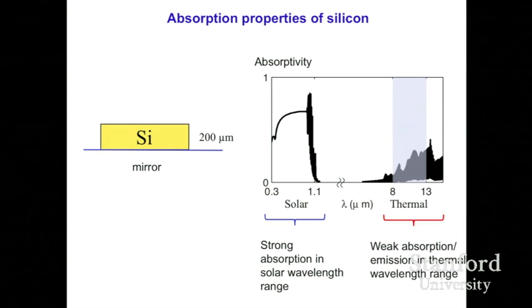So for that purpose, we examine the absorption properties of silicon over both the solar wavelength range as well as the thermal wavelength range in the 8 to 13 micron. In the solar side, of course, it's strongly absorbed. And it's also a weak absorber in the thermal radiation side, and therefore it doesn't have strong emissivity. So a silicon solar cell by itself, a silicon layer by itself, has relatively weak thermal emission and will not cool by itself.